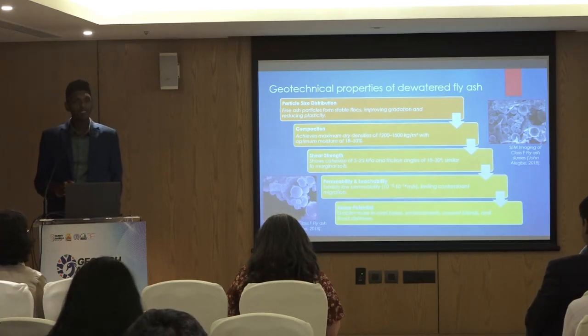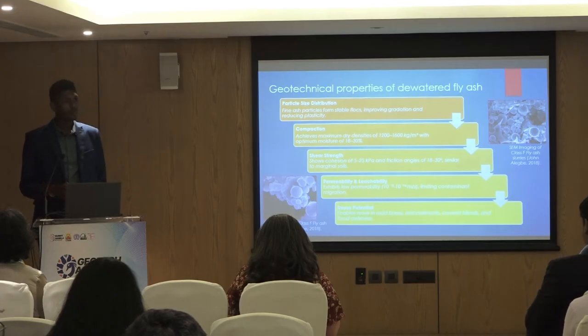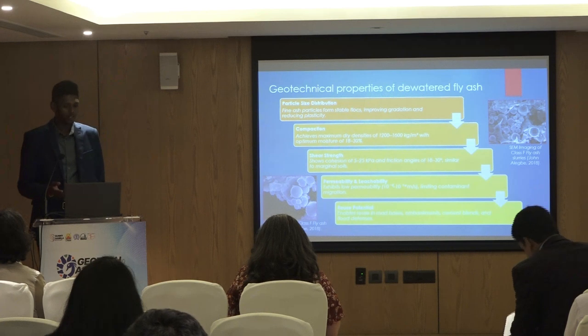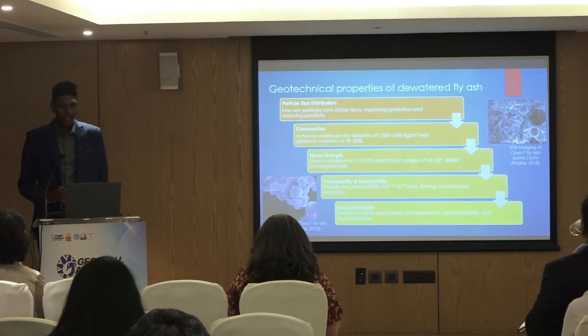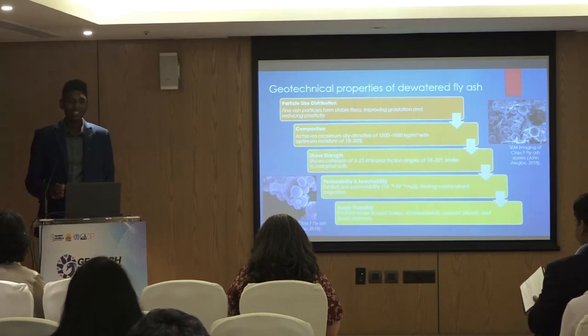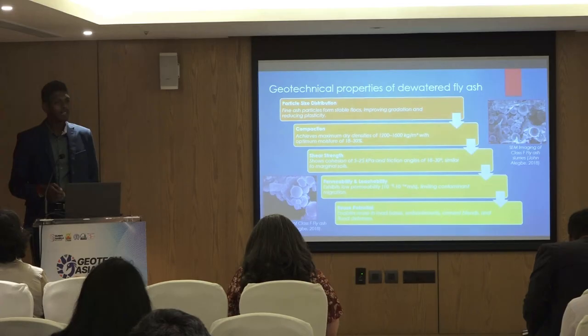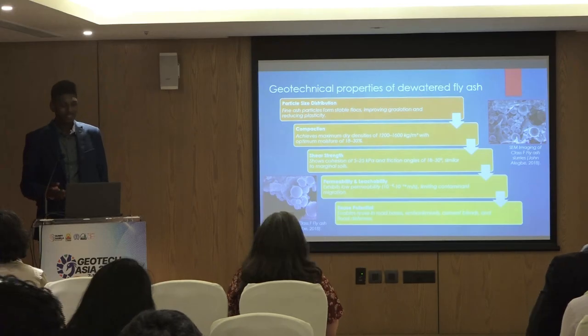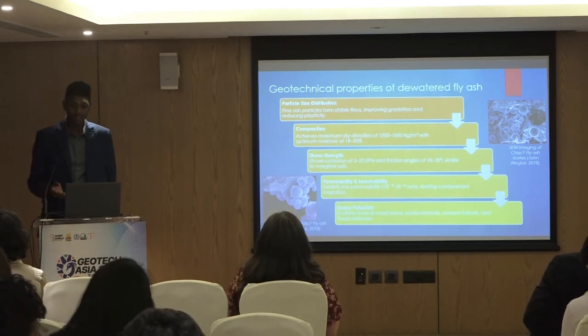Third, shear strength. Cohesion values range between 5 and 25 kilopascals and friction angles between 18 and 30 degrees, on par with marginal soils, which allows for use in non-critical layers or confined applications. Fourth, permeability, which is closely comparable to silts. It effectively limits leachate migration while aiding drainage control. So these properties enable applications in sub-bases, lightweight embankments, blended cements, replacing up to 30% of Portland cement, and even flood defenses when integrated with geotextile tubes.